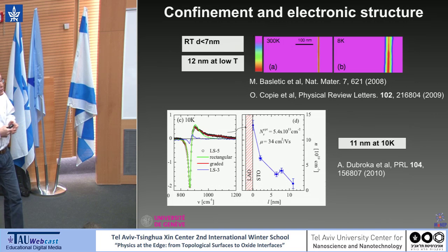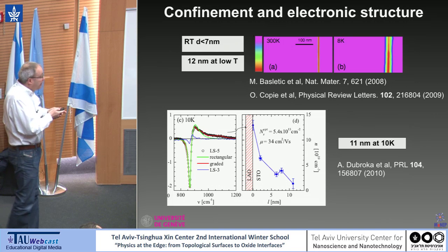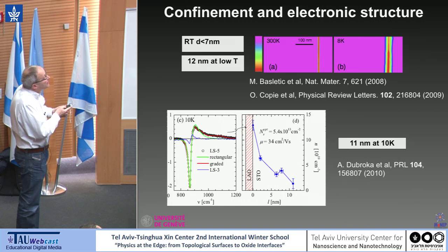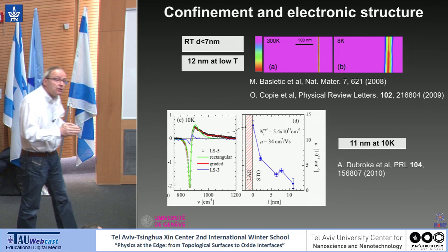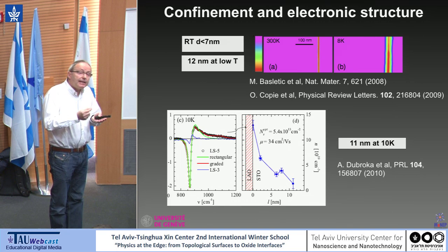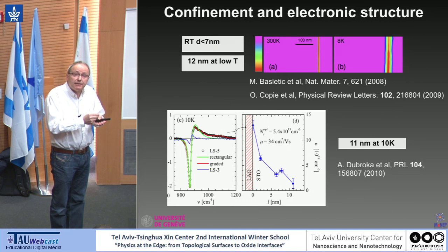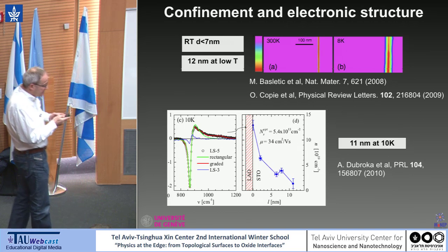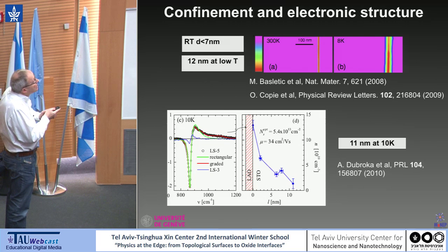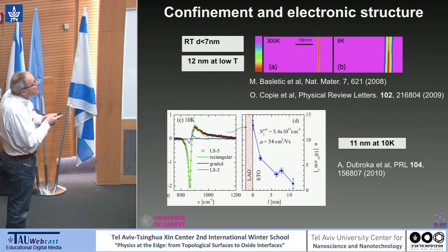Different techniques have been used. Here in Paris, what they did, they made a cross-section of a sample, and then they came with an atomic force microscope equipped with a metallic tip, and they just measured the local conductivity. And you see these conductivity maps. This is room temperature, this is low temperature, this is strontium titanate, lanthanum aluminate, and you see here at the interface the conducting layer. And you see that at low temperature, the conducting layer expands.